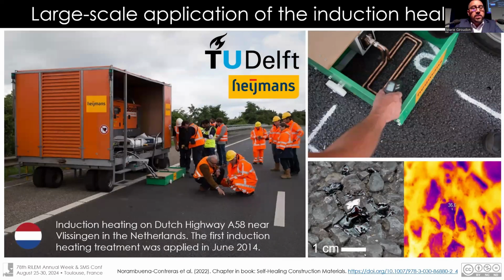Concerning the large-scale application of induction healing, the most important example was probably carried out in 2014 in the Netherlands, led by Professor Erik Schlangen. In this process, as you can see here, we use a big induction machine to heat the raw samples. Even though the technology is possible, and you can extend the surface life of the asphalt pavement by up to 50%, it is not very practical because a big induction machine is necessary to heat the asphalt under real conditions.